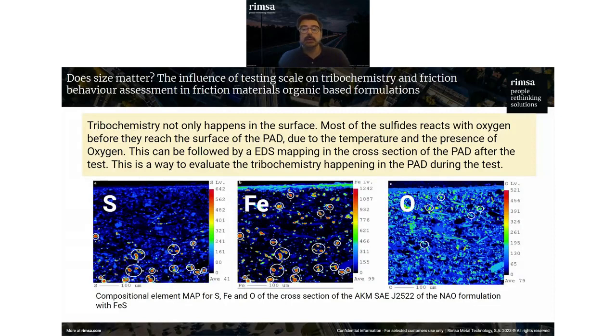In this case, one important additive of this type are the sulfides, for example. Sulfides are used in friction materials to stabilize the coefficient of friction at high temperature and to reduce the wear. But you may see here how a sulfide usually reacts with oxygen, and every sulfide has a different temperature of reaction. In this case, we are showing some results of the iron sulfide, and the iron sulfide reacts with oxygen around 400 degrees. And you can see here how after testing on a dynamometer, the signal of sulfur has gone in these first 200 microns beneath the surface.